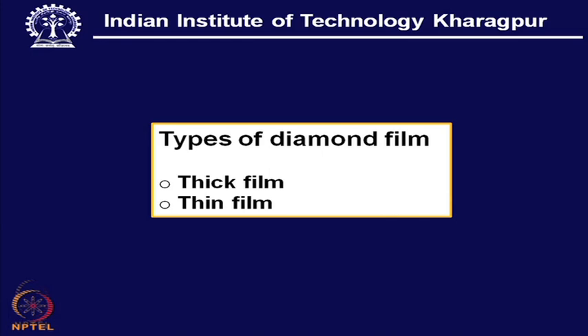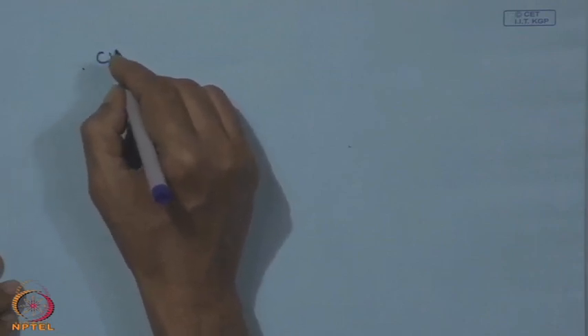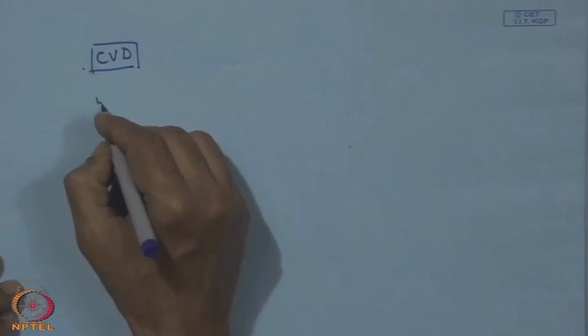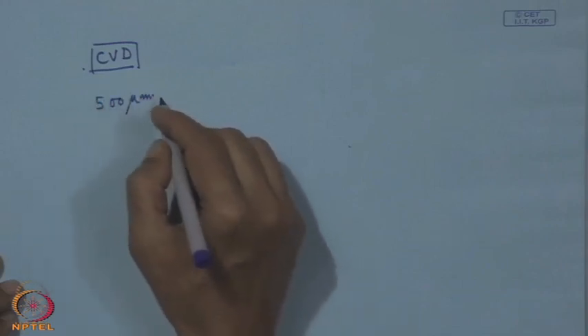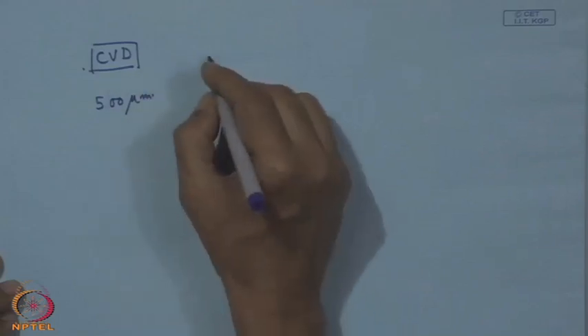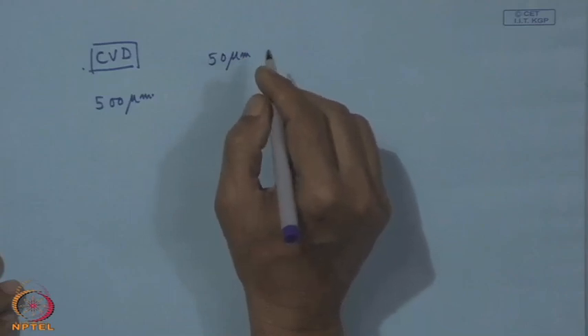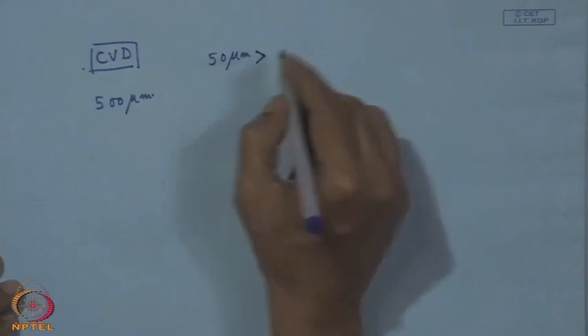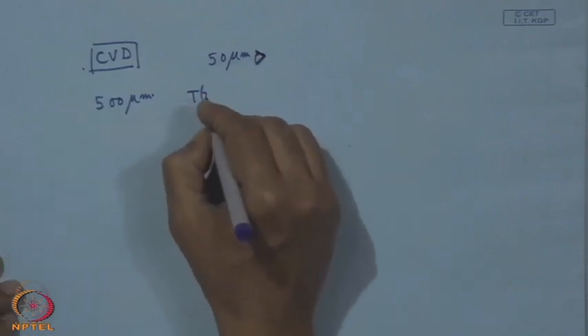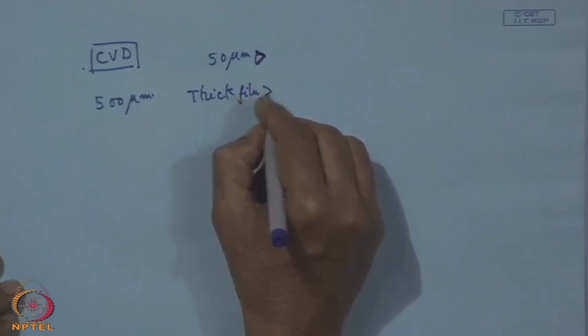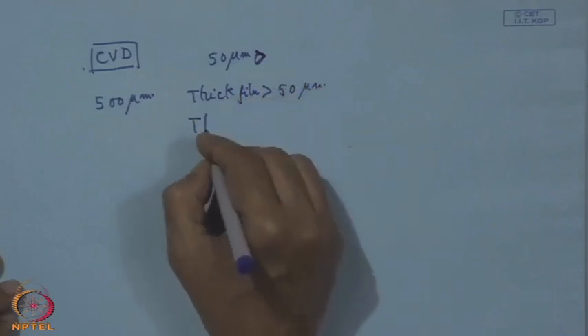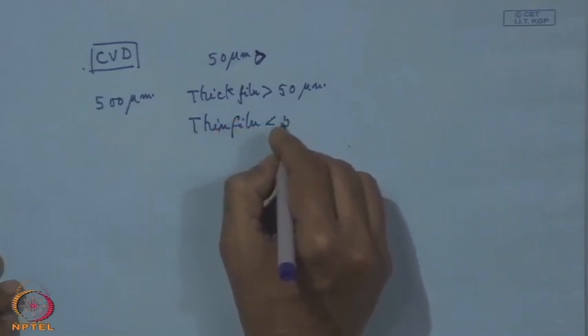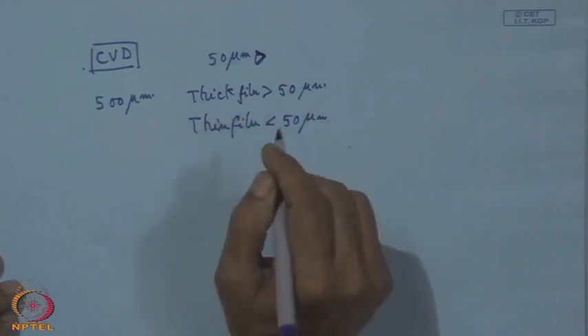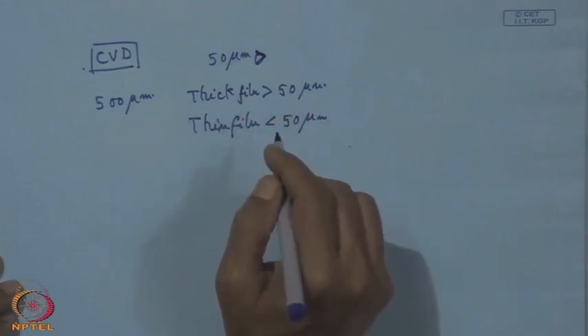Now, here we find we have both thick film and thin film. Now, thick film means we can have the CVD grown diamond, which can be about 500 micron. That means a film which is thicker than 50 micron, greater than 50 micron, we call thick film, and thin film is less than 50 micron. So, this thin film we are interested in to put directly as the coating on the substrate.